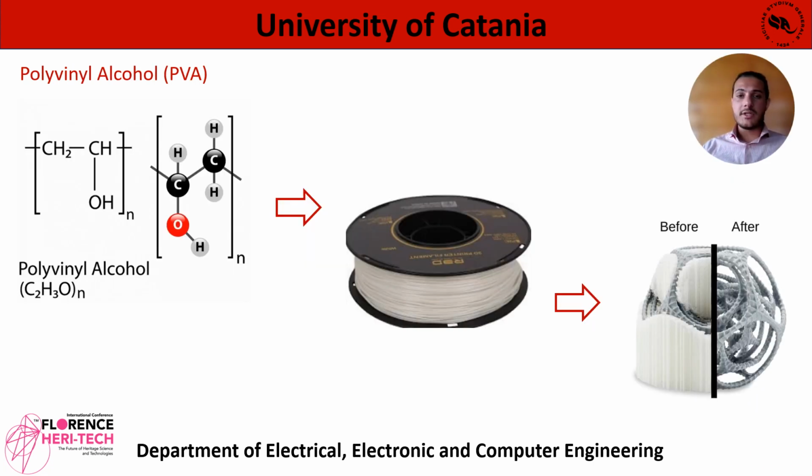The choice of using PVA consists in the fact that the polyvinyl alcohol polymer is obtained through the partial or total hydrolysis of polyvinyl acetate. The resulting PVA is soluble in water but poorly soluble in organic solvents. The degree of cross-linking determines the amount of liquid absorbed and thus the physical, chemical, and diffusion properties of the polymer and ultimately its biological properties.